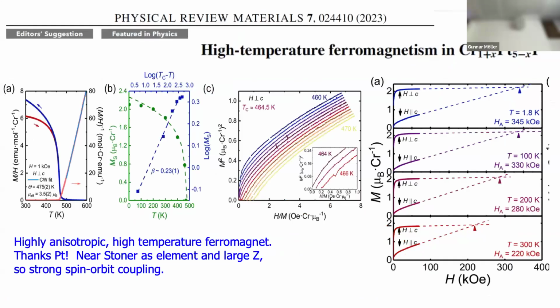Okay, so we were able to find high temperature ferromagnetism in chromium platinum 5 phosphorus. There's a small site disorder between the chromium and platinum, but we were able to parameterize it. And what's remarkable, chromium is the only moment-bearing element here. It's 1 out of 7. Okay, this is ferromagnetic just below 500 Kelvin. And as a matter of fact, what's even more remarkable is the anisotropy field between H parallel and perpendicular to C is huge. At room temperature, it's still 20 Tesla.